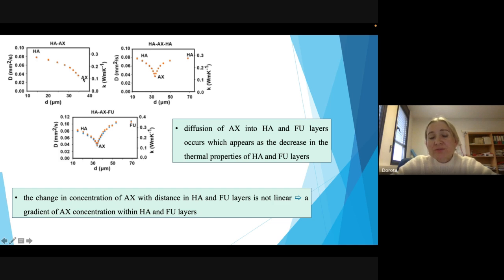That the diffusion of amoxicillin occurs in both the hyaluronic acid and the fucoidan layers. This is seen as a decrease in the thermal properties of both the hyaluronic acid and fucoidan layers. So monitoring the thermal properties of each of the sublayers can be an indication of the rate of the diffusion process of our antibiotic. It can also indicate the efficiency of the whole material as a drug delivery system.